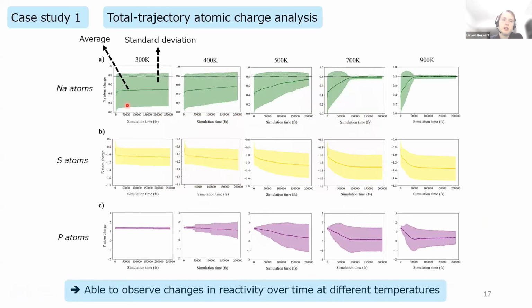And when we do this, then we see this. Because we have many atoms, more than 1,000 atoms, what I did is I calculated the average of the atomic charge separately for the different elements. This is the solid line. And the standard deviation, which I calculated, is the shaded area here. And you can see that over time, for example, sodium begins with sodium metal, charge 0, and sodium ions, charge 1. And so what happens is over time, sodium metal reacts. So the standard deviation decreases as now only one type of species, sodium ions, is left.